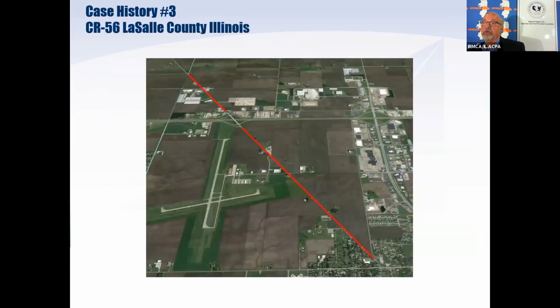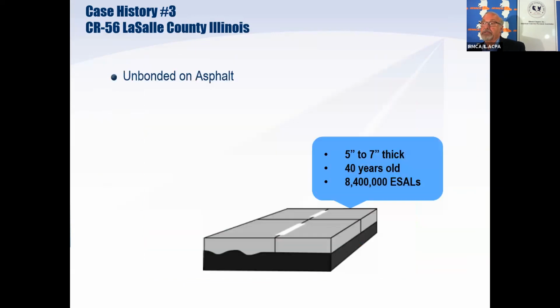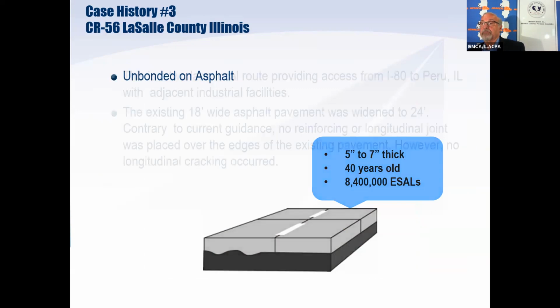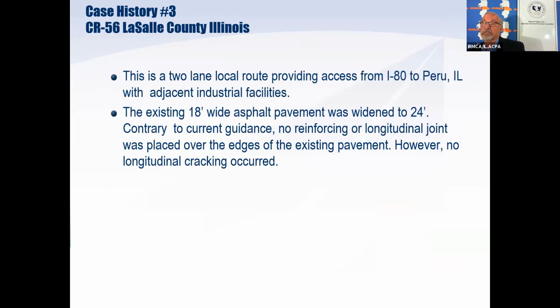And here's one from Illinois. County Road 56, LaSalle County. You can see the alignment. It's 5 to 7 inches thick and 40 years old. It's carried, and this is a few years old data, somewhere in the neighborhood of 9 million equivalent single axle loads. It's unbonded on asphalt. Common sense would tell you, based on what I've said before, that you need a thicker overlay. But this overlay has performed extremely well.